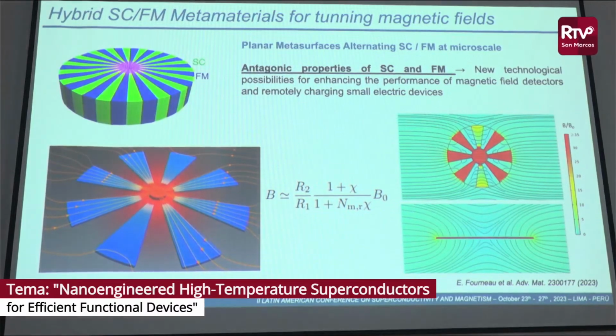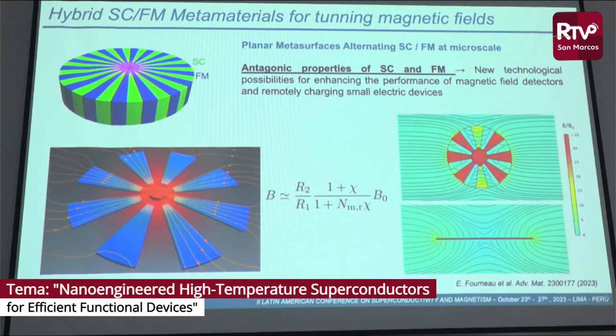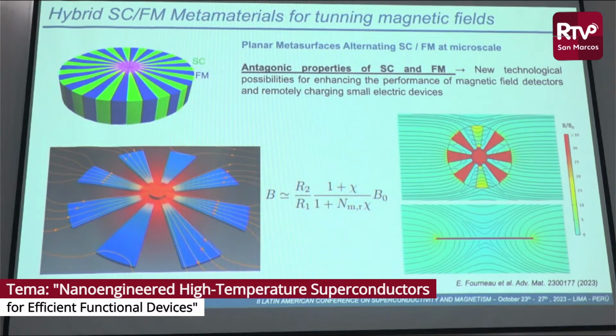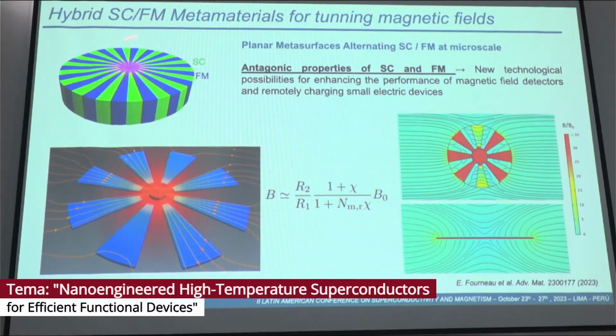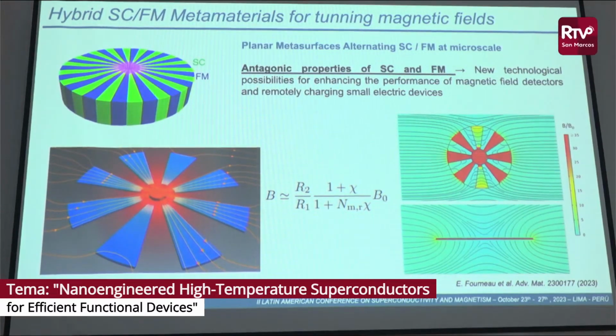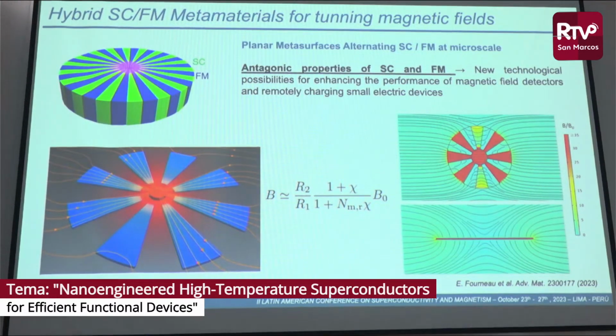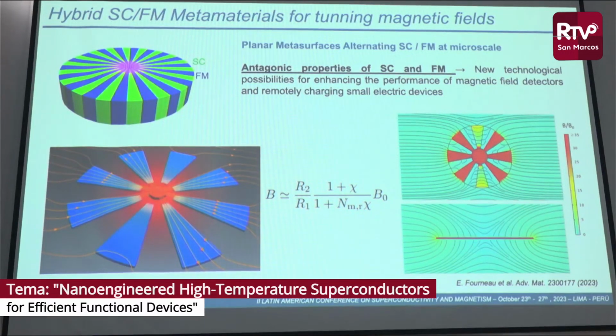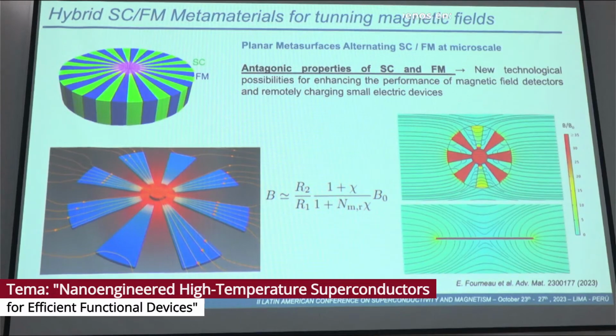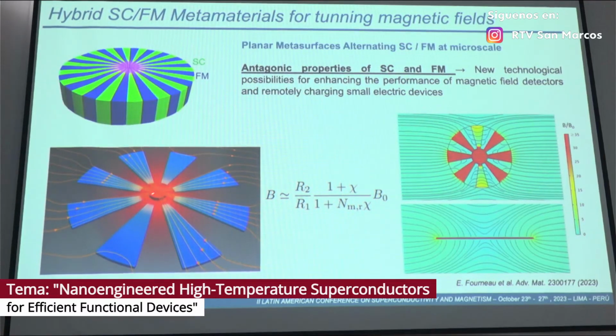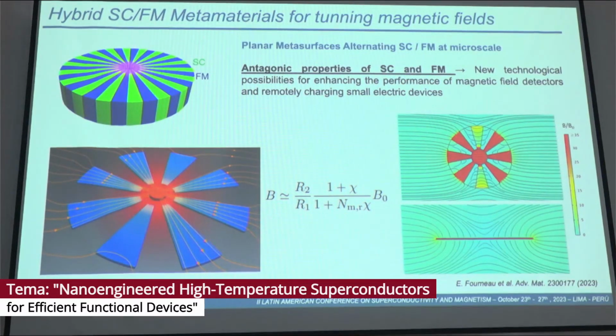And since a superconductor is a material that tries to repel magnetic fields, and a ferromagnet is a material that tries to keep all the magnetic field inside, if we combine these properties in a clever structure, what we can do is to play with the magnetic field and play with the properties of this magnetic field. And in particular, what we have explored is these flower-shaped structures where we can combine superconductors and ferromagnets, or just work with a ferromagnet, which is also possible because you just don't need the superconductor. The superconductor just improves the properties of the material. And what you create here is a concentrator of the magnetic field, which could be used to enhance the properties of a magnetic system.